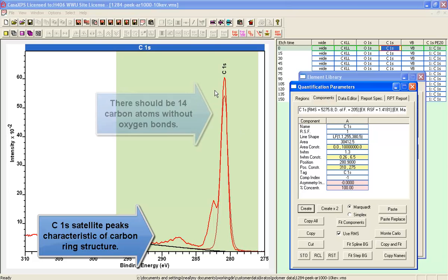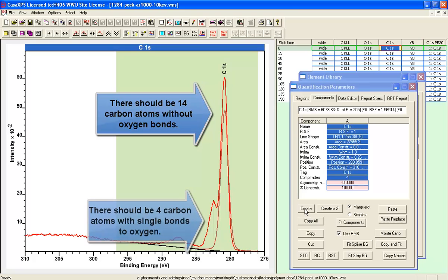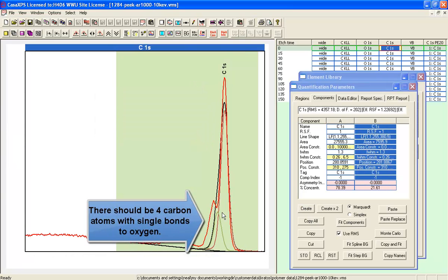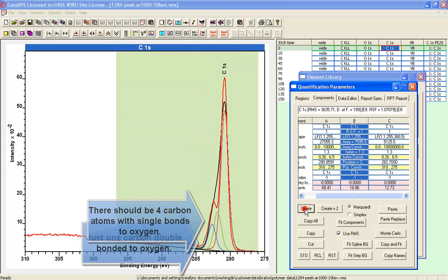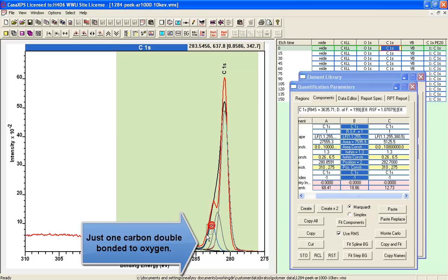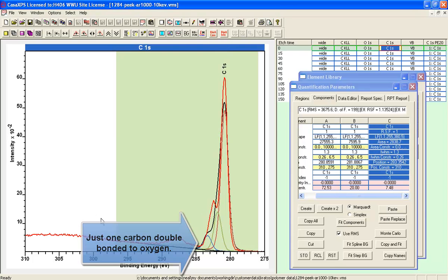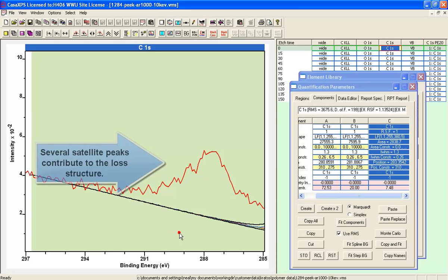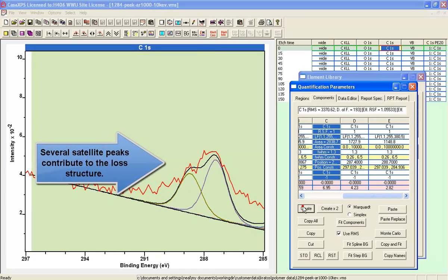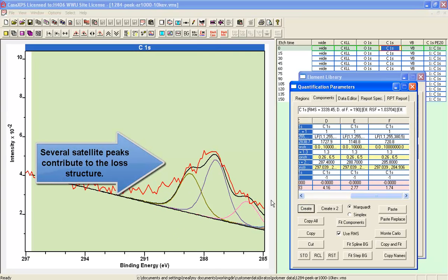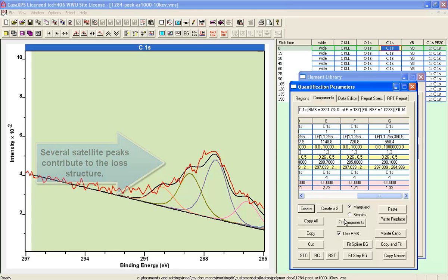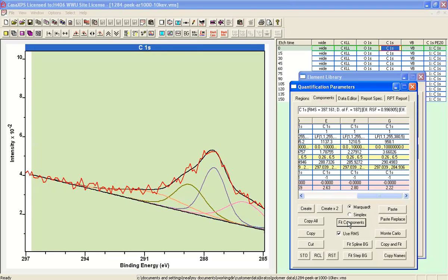Looking at the carbon 1s, you can see there are satellite peaks and then there are the main primary peaks. The primary peaks ought to be in the ratio of what is expected for polyether ether ketone. The carbon 1s also has peak structure that is associated with these benzene rings and satellite peaks, so we have to account for these in the peak model.